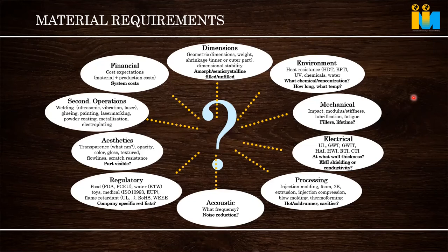Then whether this raw material part is going to come in contact with water. Some of the materials are very sensitive to water absorption. For example, we are using plastic in a razor, Gillette razor, everybody has seen. In that razor blade, those plastics are made of PPO. PPO means Noryl grade from SABIC. That is the polymer which absorbs the least moisture. Most nylons absorb 2 to 3%, and PC absorbs up to 0.5%, but Noryl or PPO absorbs only 0.1%, and it is amorphous also.